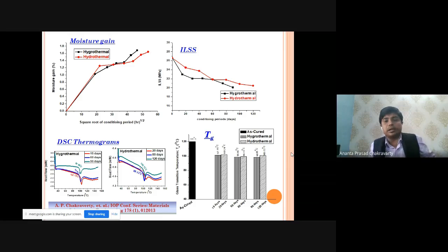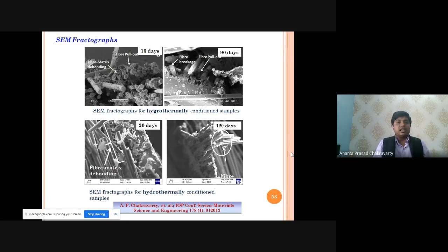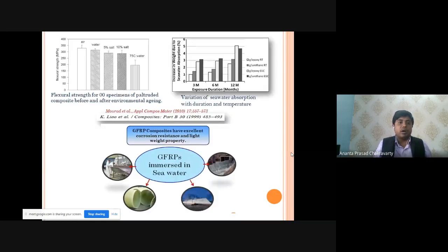It is a crucial parameter for FRP composites, and it decreases up to a certain extent, and up to that design stage, you have to fabricate your composite materials so that they can be applied in aerospace or in applications where moisture is there. Similarly, thermal properties decrease up to a certain percentage, and at that level of glass transition temperature, you have to go for fabrication. And in its micrographs, you can see how materials break by fiber breaking, polymer crushing, and fibers being pulled out. In that way, your microstructures can be understood.